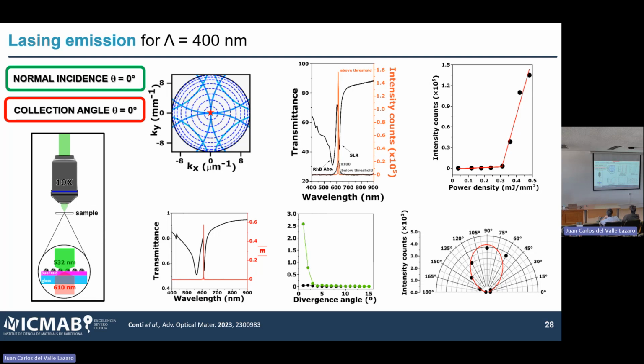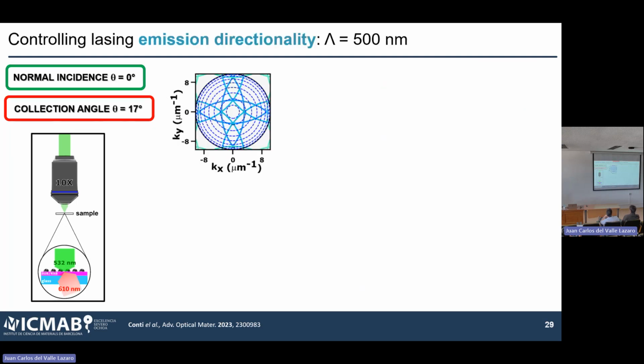And so then, as I said, this system is very versatile. So we started to say, okay, what happens if I change the lattice parameters? So in this case, I'm changing the lattice parameters, so I'm changing all the plasmonic and optical properties of the system. And so what happens is that now I should expect lasing activity not at the center, so not coming out normally, but at a certain angle. It's represented here, right? I should illuminate from the normal direction, and I should expect my lasing coming out at an angle.